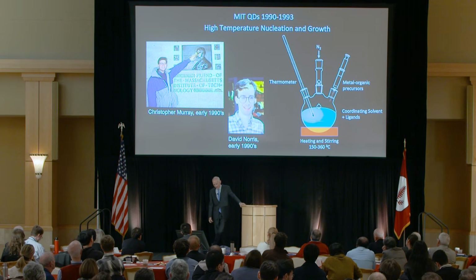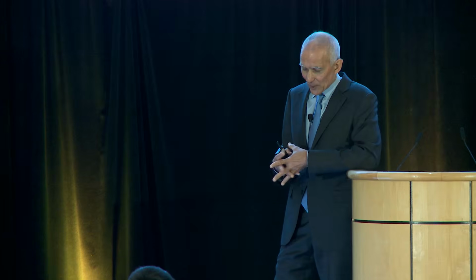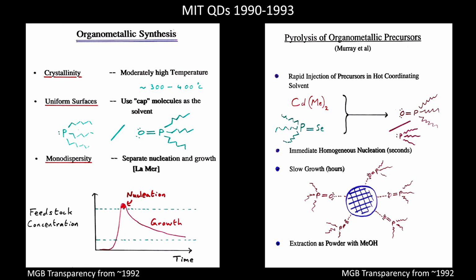And it worked. It worked. We were able then to create a size series of these particles. You know, Chris did an incredible job of learning polymer methods also to be able to purify these things. And now I have a laser printer. You know, it's 1992 or so. Laser printers are available. And these transparencies have both handwritten and typed things. And you can see it, you know, the really simple idea. High temperature, uniform surfaces, all the same molecule, the nucleation and growth, the rapid injection, and then the extraction as a powder based on what Steigerwald had realized using the aqueous thing.